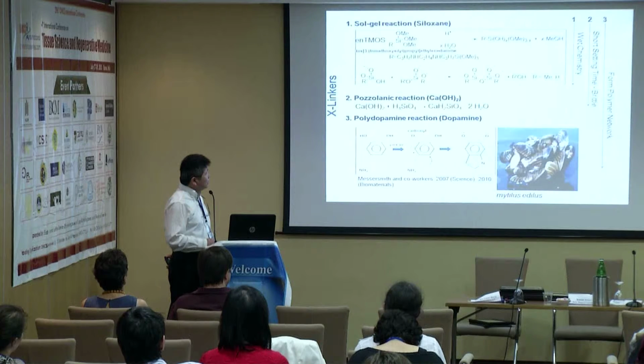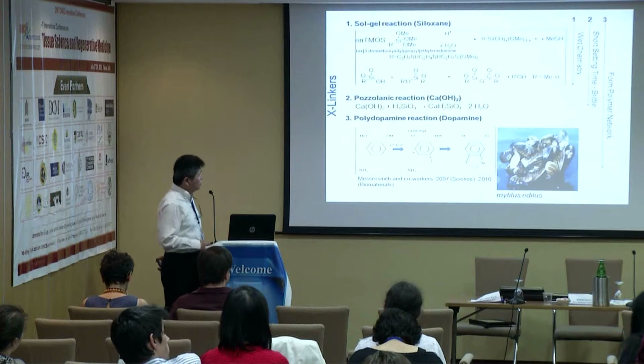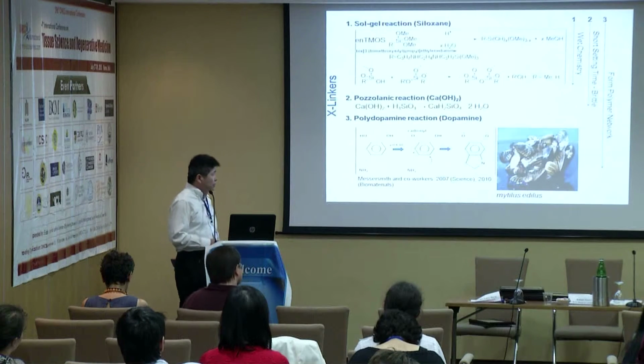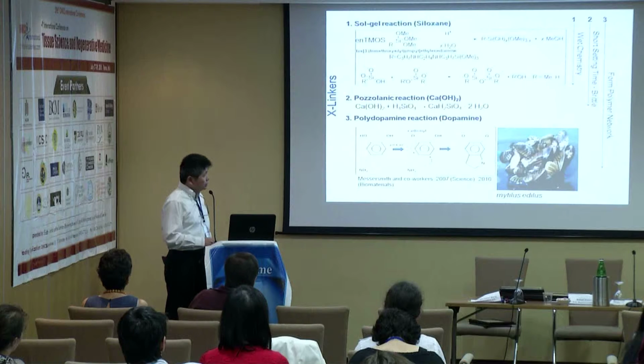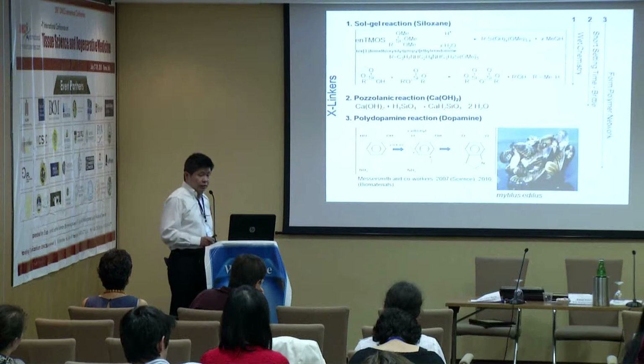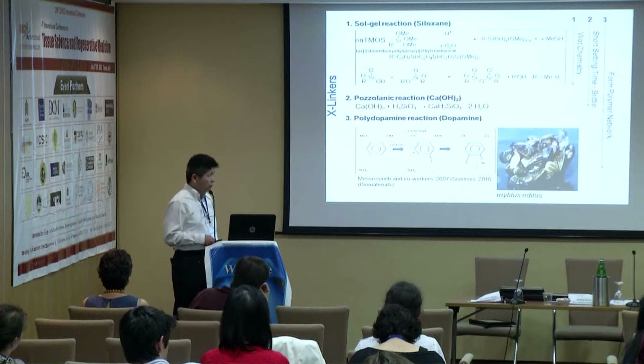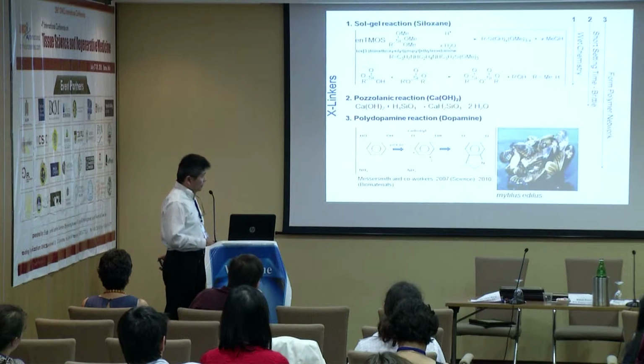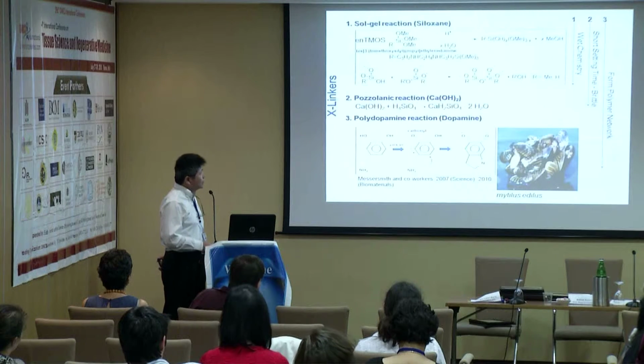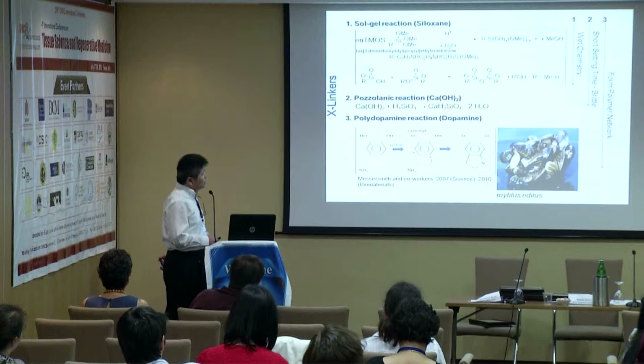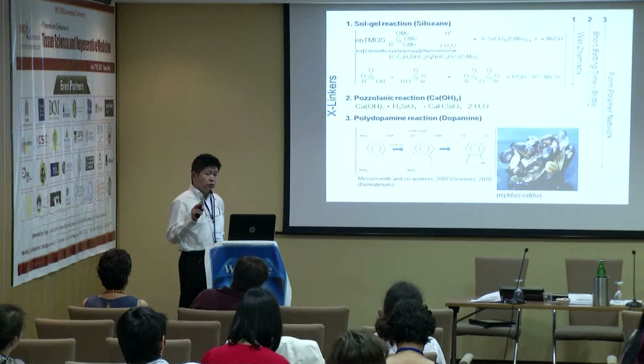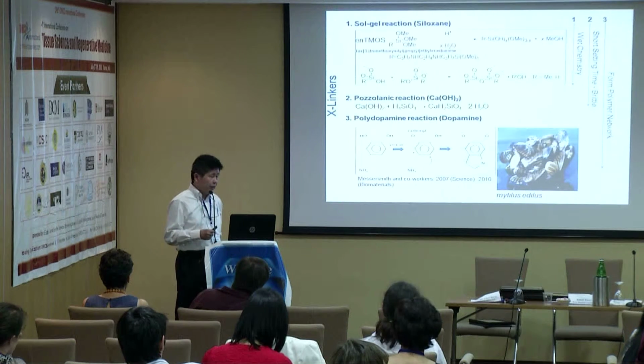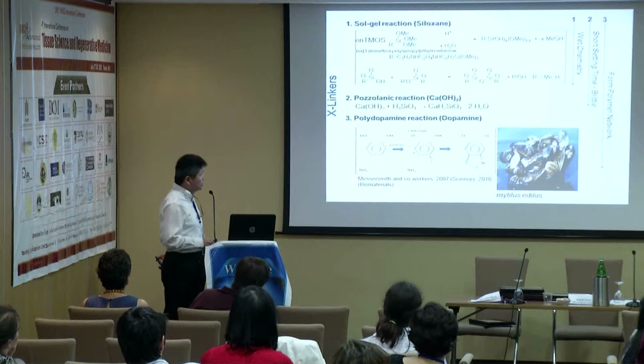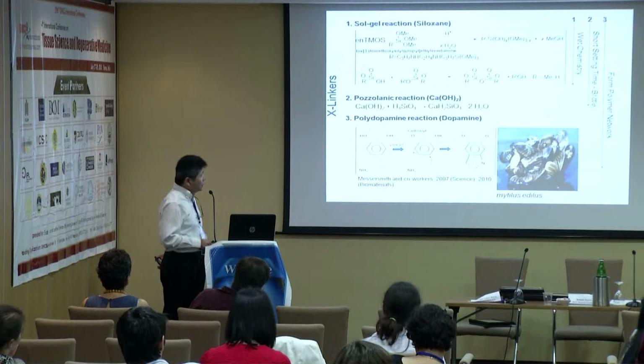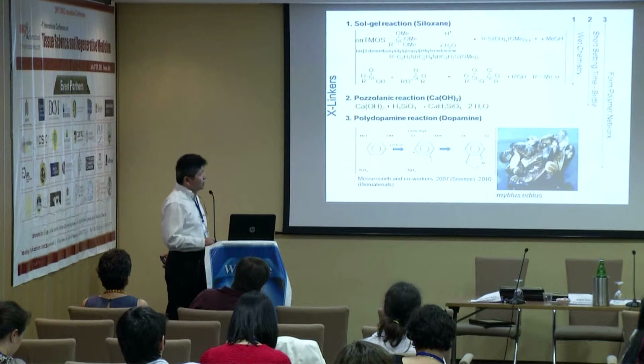And most recently, we add another reaction, which is the main topic of today, dopamine, into our system. Because dopamine protein is present in a lot of things, like mussels. When they attach to the rock, they're using a majority of the dopamine protein there, and this was published by Messersmith in 2007 in Science. Converting dopamine to polydopamine is a very simple procedure. You just change the pH value, and it's automatic polymerization. So we find it's probably a useful chemical reaction, so we added it into the system, did some testing, and found out it is helpful to our system.